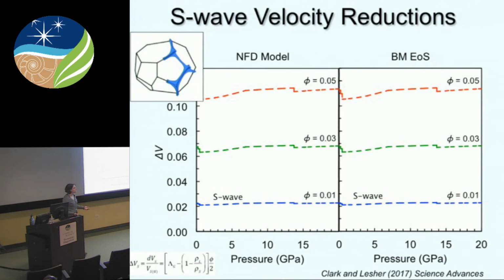Okay, so I'm going to show you now the results of my calculations. We're going to start with S-wave velocity reductions as a function of pressure. So this is the velocity reduction, so larger velocity reduction going up as a function of pressure. And I have here the results calculated for the equilibrium melt texture. The results are generally the same for any melt geometry. What you can see here, perhaps not surprisingly, is that the calculated velocity reduction is the same for both the network flexibility model and the Birch-Murnaghan equation of state.